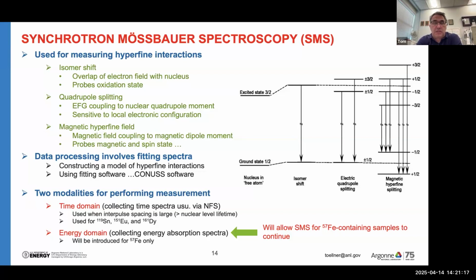And this approach for Mössbauer spectroscopy is applicable when the interpulse spacing between the X-rays is longer than the nuclear level lifetime. And this remains the case after the upgrade for tin 119, europium, and dysprosium. They're all in the 10 to 30 nanosecond nuclear level lifetimes. And so the approaches there will remain the same. In the case of iron 57 with a longer lifetime, we have to introduce an energy domain approach in order to get a sufficiently wide time window for meaningful extraction of a spectrum.